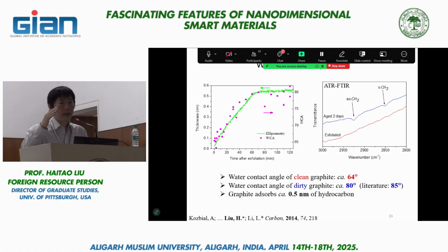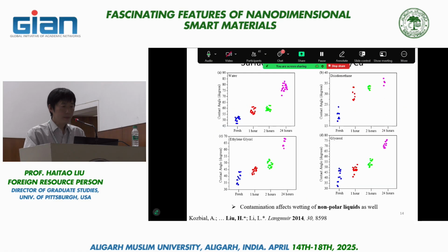This behavior persists even if we are using diiodomethane, which is a relatively non-polar testing liquid. This again is surprising, and we didn't expect this. Initially we thought we have organic molecules on the surface, and if you are using an organic testing liquid, they're going to be dissolved, so it shouldn't have any impact. But no, we still see the impact. So the implication is that those organic molecule contaminants are likely pretty sticky. There might be a much stronger interaction than we thought between those molecules and the substrate, to the point that using diiodomethane, you cannot dissolve them or release them from the surface.